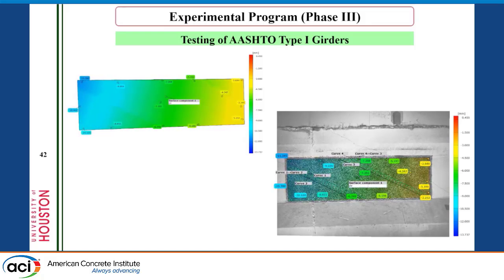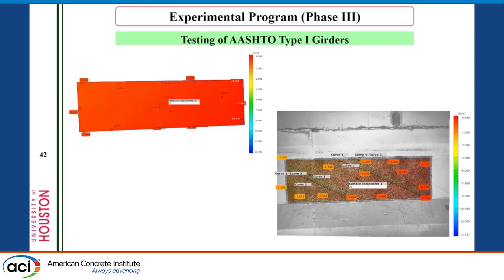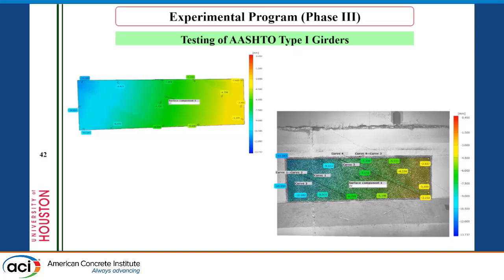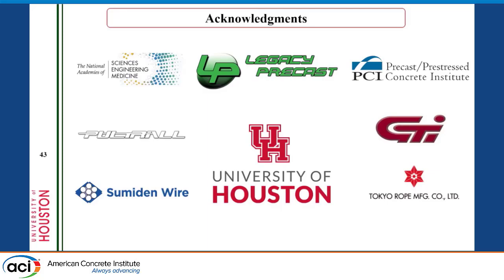And here is just a mapping using DIC. When we analyze what's going on in the testing regions in terms of strain, we can get it at any level, including crack width, and this would help a lot, since we can get the stresses from here if we get the strain. We're still analyzing this data. And that's the last test we performed recently. Thank you for your attention.